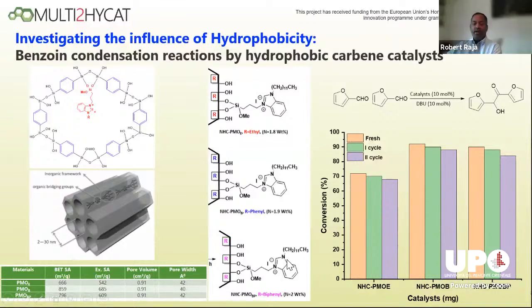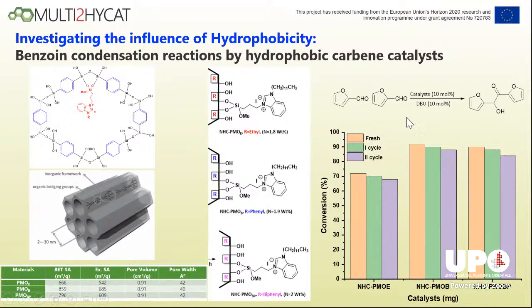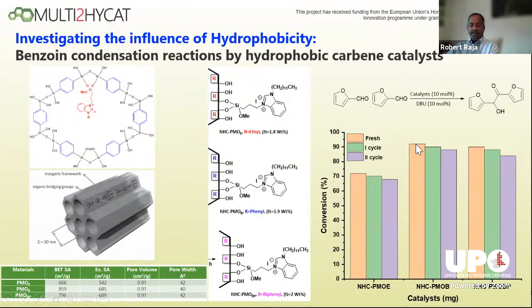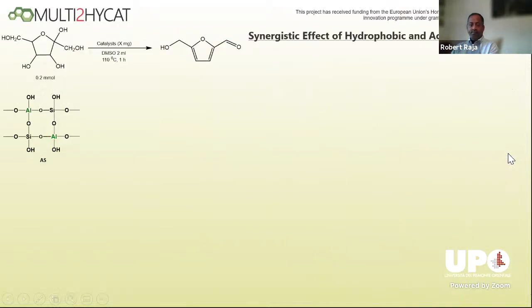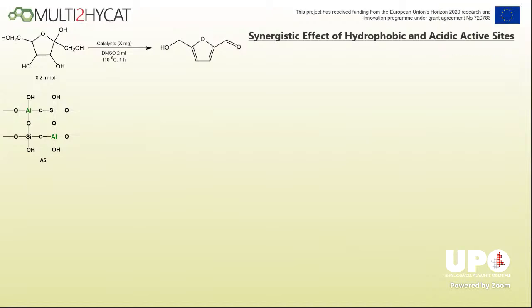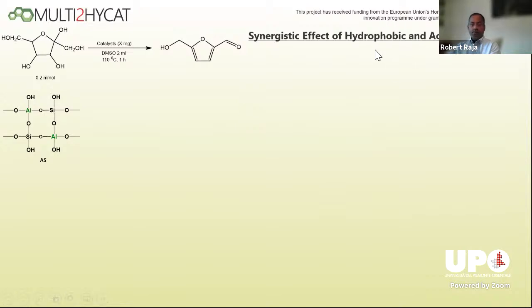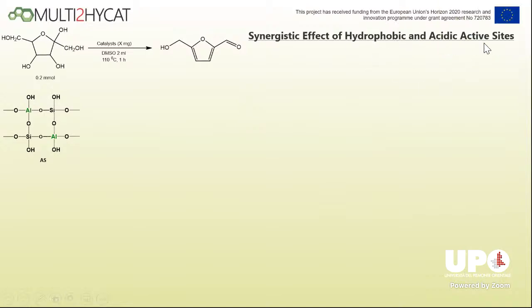Yes, correct. Okay. So what I was really showing here was by introducing these different hydrophobic moieties, one can significantly enhance both the catalytic activities of these materials, but also their recyclability. And then I went on to explain some of the structure property correlations that we had established as part of this project. In particular, with these periodically ordered mesoporous silicas, one can probe the hydrophobicity, as I showed you earlier, but also one can start to introduce acidic sites.